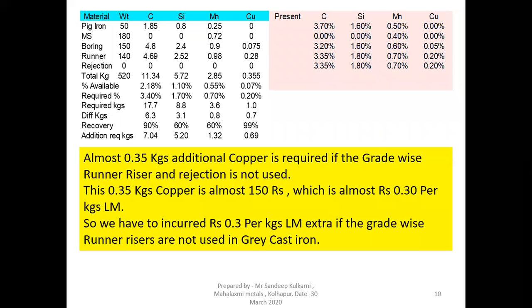In the second slide, the copper content in the riser is 0.2%. So the requirement of copper is now reduced to 0.69 kg — almost 700 grams. This means almost 350 grams of additional copper is required if grade-wise runner risers and rejections are not used for the higher grade. This 0.35 kg of copper costs almost 150 rupees, which is almost 0.3 rupees per kg of liquid metal.